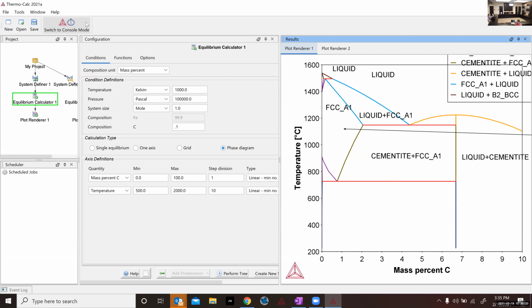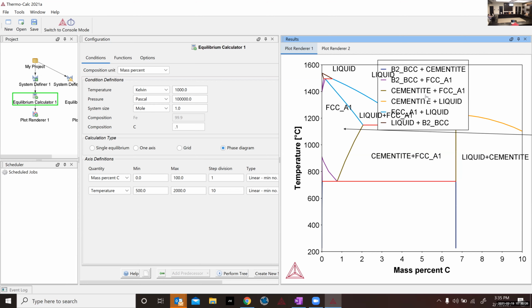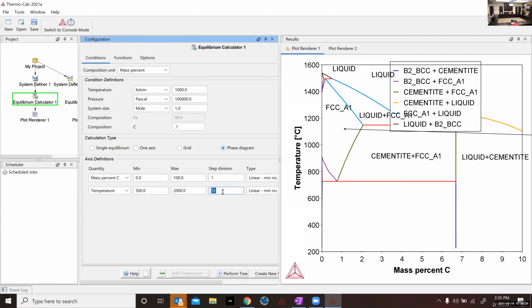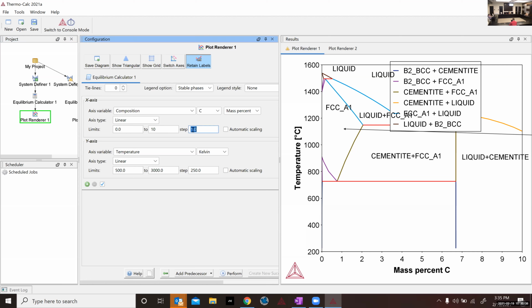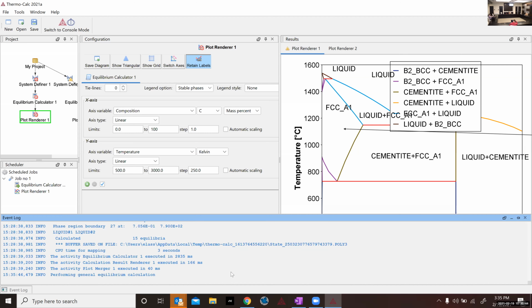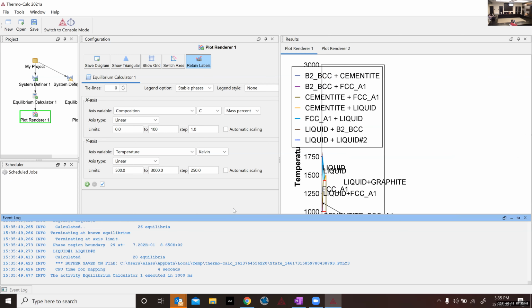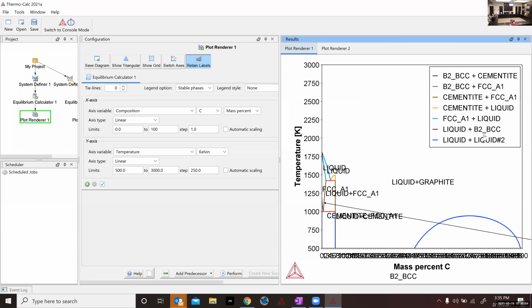What's that? Where? Oh, so after we removed the cementite, I expanded it out because I was like, well, it keeps going down, and then it says that that's a liquid and cementite region. So then I expanded it out to look at it, and if you do it up to 50 is where the second liquid region starts, but it's just... This is probably a good time to point out I didn't... Because I was like, dang, that's a low temperature to have. I didn't carbon. Does carbon even melt? Or does it just evaporate?